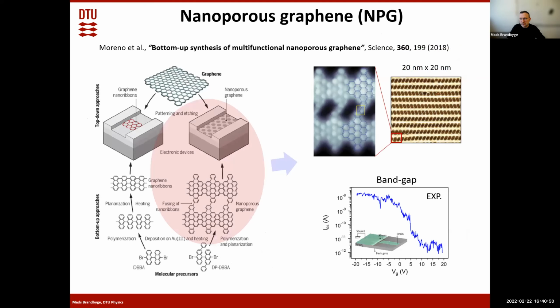Because there's of course a huge number of variations, because these materials start with a small molecule, a precursor, and then you see you have these bromines here, and once you put this molecule on a metal surface, on the right metal surface, like gold 111, they will actually attach together like Lego and build these structures here.